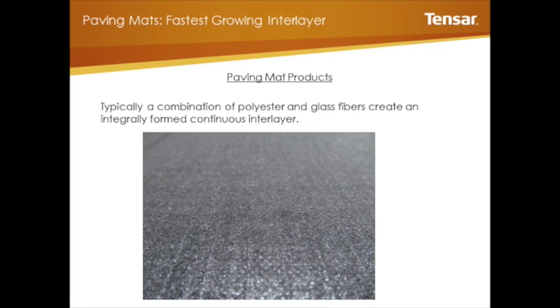And when you include a non-woven paving fabric in your structure, the incidence of fabric in your RAP mix prevents you from reusing it as is. So it typically has to be screened, and it's a very expensive exercise, and most contractors do not wish to do that. So it's important for you to keep in mind that when you are specifying paving fabric, you may have an issue with respect to the RAP not being able to be used in the future. There are some facilities in the United States that can screen the material, but very few. I think I can think of 2 at present. So that is a consideration.